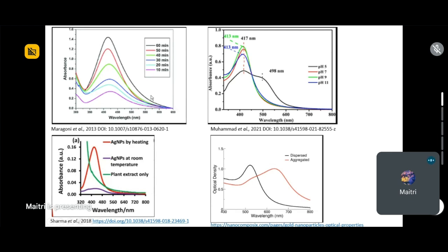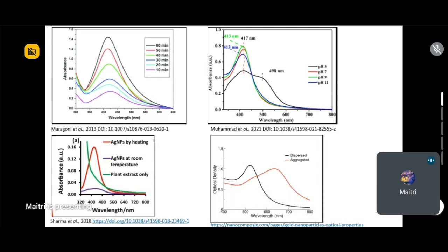So see, these are some figures which have AgNPs being synthesized. And just see, like in the top left one, what is happening is here this person is trying to standardize the protocol for the best time of the reaction. So just see, like the purple one is telling that after 10 minutes only this much is formed. Then after 20 minutes a little more. Then after 30 a little more, and so on. At 60 minutes, you have the maximum formation of the silver nanoparticles, such that the peak is also very sharp and it's giving you a very nice OD reading at 1.4. And it's giving you exactly at 420, 425 nanometer, which also tells you that the silver nanoparticles have formed. So this tells you that it can be used for adjusting the time, temperature, pH, and many such parameters of your reaction.